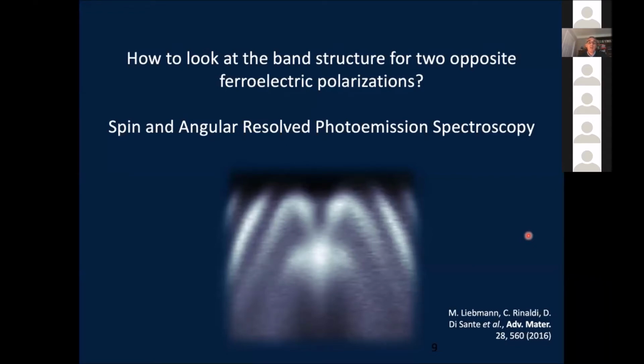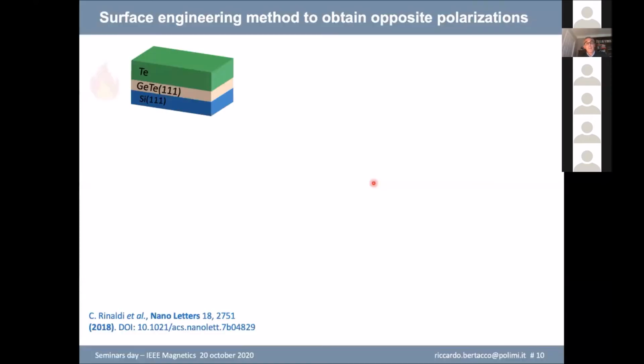You see the typical shape of Rashba bands, even though the Fermi level is here. And the reason being that germanium telluride is a p-type material due to germanium vacancies, so that the Fermi level is cutting the valence band top. Okay, the bands are okay, but the problem was, how can you play now with the ferroelectric state? It's not so easy to carry out an experiment in which you pull your ferroelectric film, because in principle with spin and angle-resolved photoemission, you need a surface, a clean surface. Having an electrode, the top electrode, is a problem.